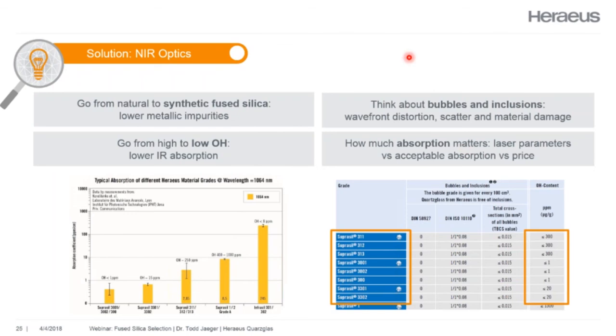There we go. So for the best performance in the near infrared, you want to go away from a natural fused quartz towards a synthetic fused silica. This is going to give you lower metallic impurities, which can cause absorption. You want to go, instead of a high OH material, you'd like to choose a low OH material, which will give you lower infrared absorption.